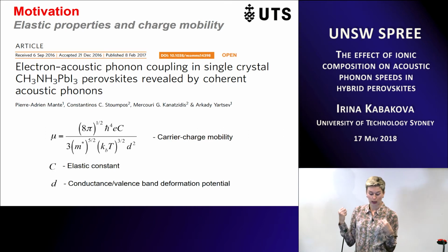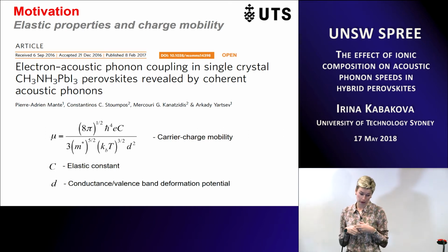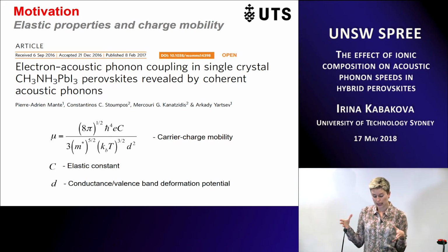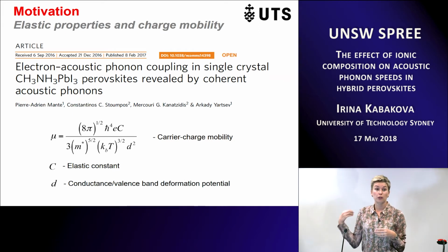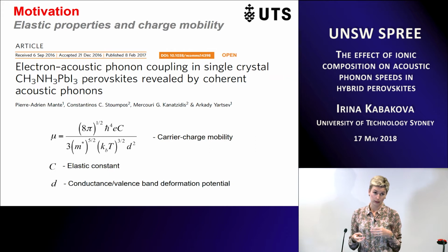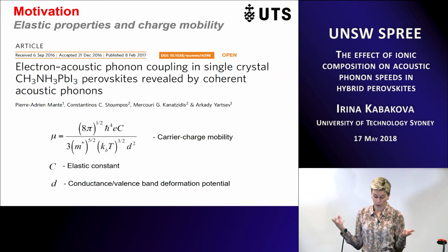And this article, which was published in 2017, clearly stated that the charge carrier mobility is directly linked to the elasticity of the material, the elastic constant C in that formula.